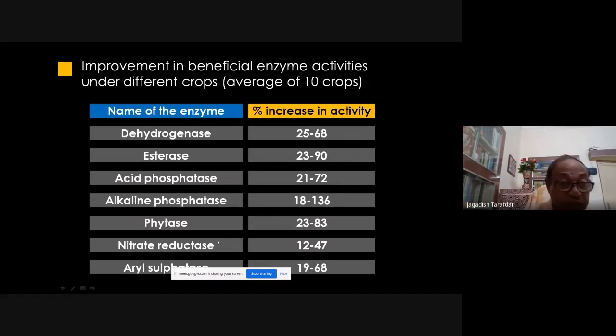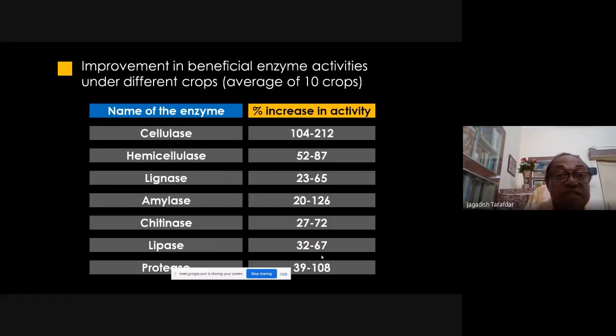Nitrate reductase, nitrogen mobilizing enzymes, you see 12 to 47% increase. Aryl sulfatase, 19 to 68% improvement in sulfur mobilizing enzymes. Again, you can see the cellulase, hemicellulase, and lignase. These three are degrading enzymes. This degrading enzymes activity is increasing 23 to 212% with this triggering.